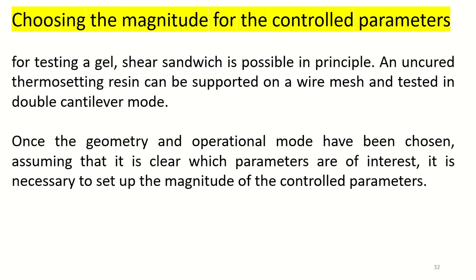Once the geometry and operational mode have been chosen, assuming that it is clear which parameters are of interest, it is necessary to set up the magnitude of the controlled parameters. This is especially true with dynamic mechanical experiments where one parameter should be kept constant. So we should be aware, before performing the experiment, of the magnitude in which one parameter should be kept constant. To illustrate the problem, consider the case of a dynamic strain control temperature ramp test.